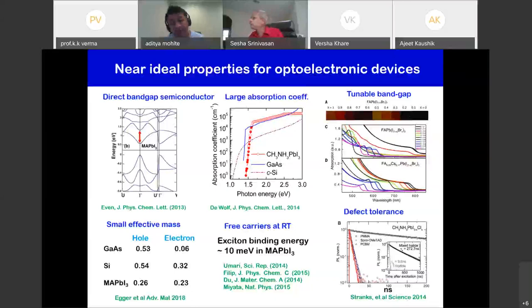Also, it creates free carriers at room temperature. What does that mean? It means that if you put light on this material, these electrons and holes are not coulombically bound. They are opposite carriers, and the binding energy in this is very small, about 10 milli electron volts at room temperature. As soon as you form these electrons and holes, they are not talking to each other. They are not bound tightly. You can easily dissociate them.